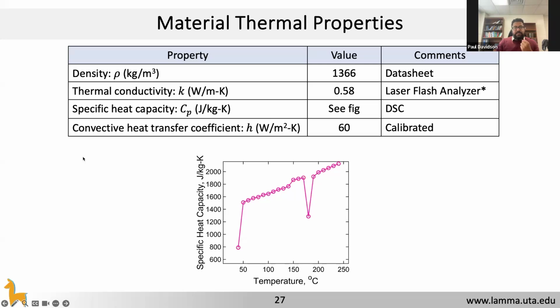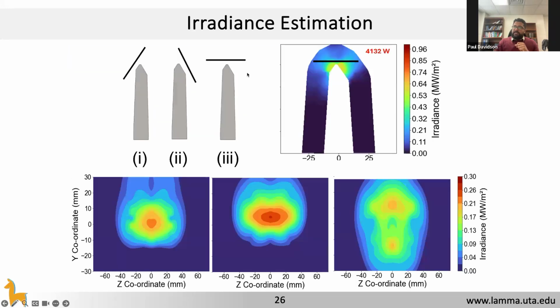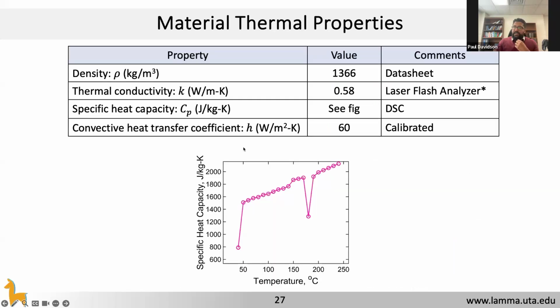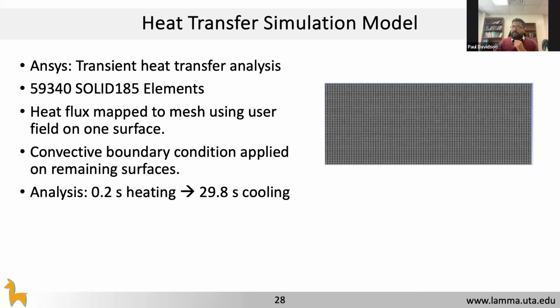And as you know from basic thermal engineering classes which you have taken, this heat transfer coefficient is extremely dependent on how the air moves around the tape itself. So for example, the convective heat transfer coefficient parallel to facet 2 versus parallel to facet 3 can change because of the way air is heated around the tape during each of these experiments. So we did calibration for one of the experiments and then used that to see how best we can replicate the other experiments.